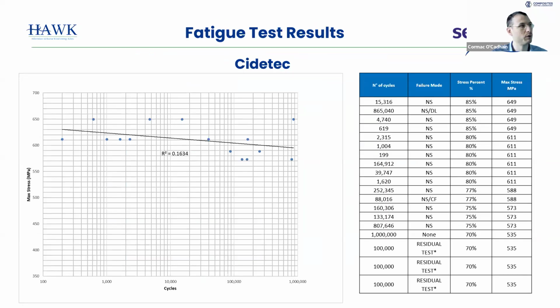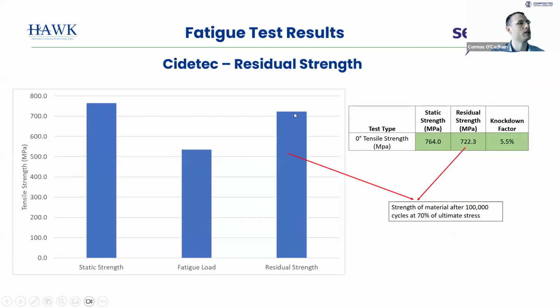So I'll kind of breeze through the last couple of slides. So we did fatigue testing on this Cidetec resin. We got our SN curve here. There was a good bit of scatter in these results, but in general the trend was quite good. We then tested three specimens to 100,000 cycles at 70% of the load. And they didn't fail. So we ran those and we stopped at 100,000, and then we tested them afterwards to see what the knockdown factor is here. So that's our static strength of 764, and then a residual strength after fatigue of 722. So it's a knockdown of about 5.5%. So that would give designers an idea of the effect of the fatigue life on the material.